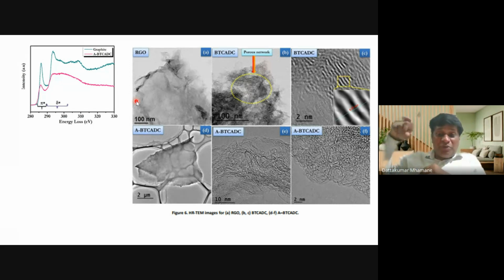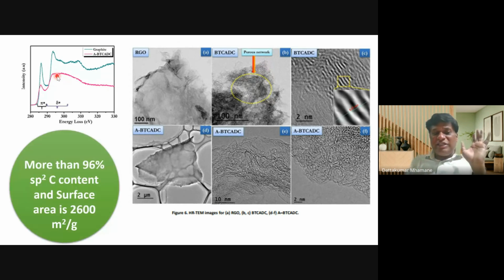So that was one of the challenges I showed you in the previous slide. How your graphene is going to reach in sp2 carbon content, that is also something we undertook as a challenge. We stitch small benzene molecules together, and we increase the sp2 content here. Graphite actually has 100% sp2 carbon, but in case of our carbon it is more than 96%. So more than 96% sp2 carbon we achieved here, and we activated that particular graphene, and we got the specific surface area of 2600.